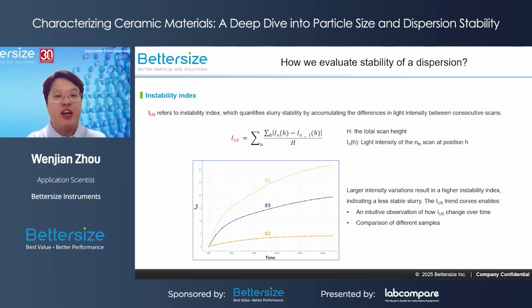In addition to qualitative analysis, we can also perform quantitative analysis using what we call the instability index, or IUS. IUS is calculated by accumulating the variations in light intensity between two consecutive scans. The principle is simple. If the light intensity changes a lot, the IUS value goes up. And the higher the IUS, the less stable the system is. Now, because each scan provides a new IUS value, we can generate an IUS trend curve over time. This allows us to see not only how quickly the IUS increases, but also how long it takes for the IUS to reach a certain value.